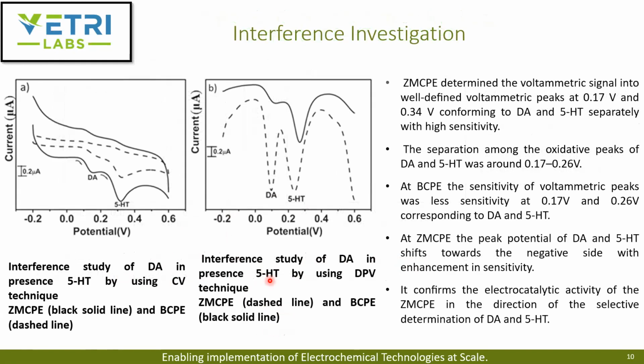Ideally, when you measure in blood serum, you don't have just serotonin, you have a mixture of other biomolecules like dopamine and adrenaline. So they wanted to know the interference of the other components in the investigation of serotonin. For this, they used dopamine. As you can see, the zirconia modified carbon-based electrode had a well defined voltammetric signal with peaks at 0.174 volts and 0.34 volts, confirming the separation. The peaks were separated for both dopamine and serotonin, and there was no interference.